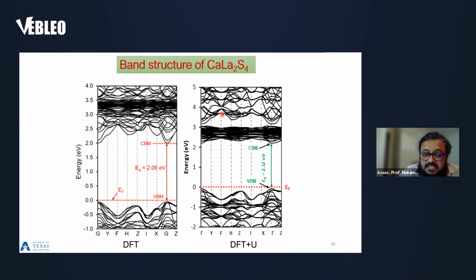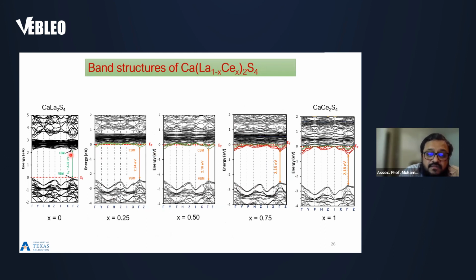Within this formalism, it shows a charge transfer type Mott insulator. Even though this has limitations, as I just mentioned, for DFT plus U, this overall feature seems to be correct according to experimental mobility measurement. Now, these are the band structures for all of them from x equals 0 to x equals 1.